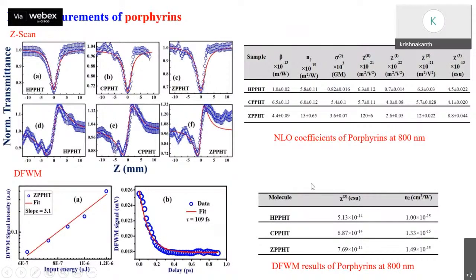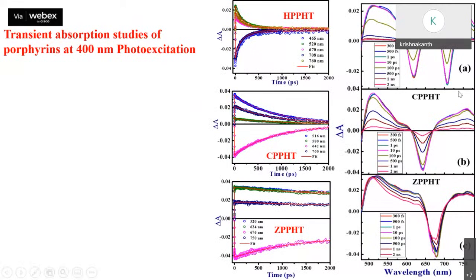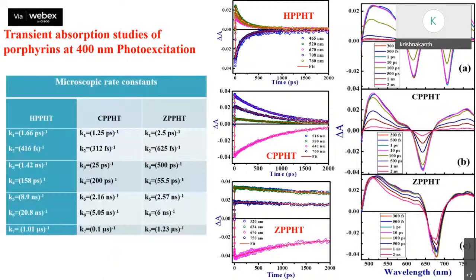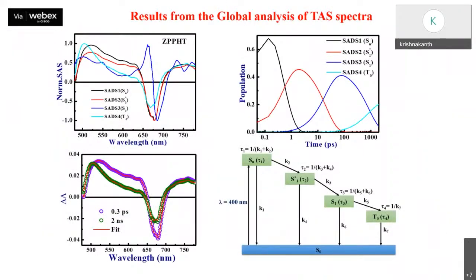As you can see, the NLO parameters are quite strong in zinc porphyrin. Then you move to the excited state dynamics. From the excited state dynamics, you can clearly see that the Zn has strong excited state properties. From the Z-scan and transient absorption, we can say this is having strong excited state properties from zinc, and a strong heavy atom effect, which is mainly showing its higher magnitude of chi3. And this is the result from global analysis of the transient absorption spectrum.